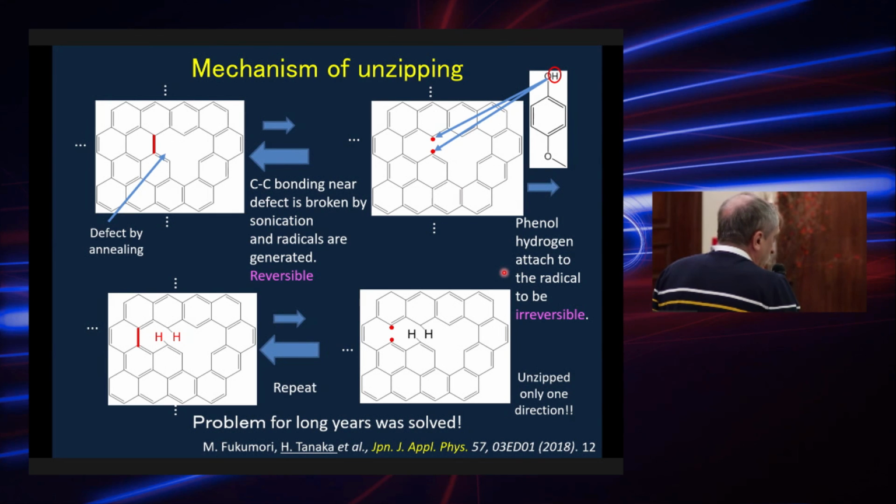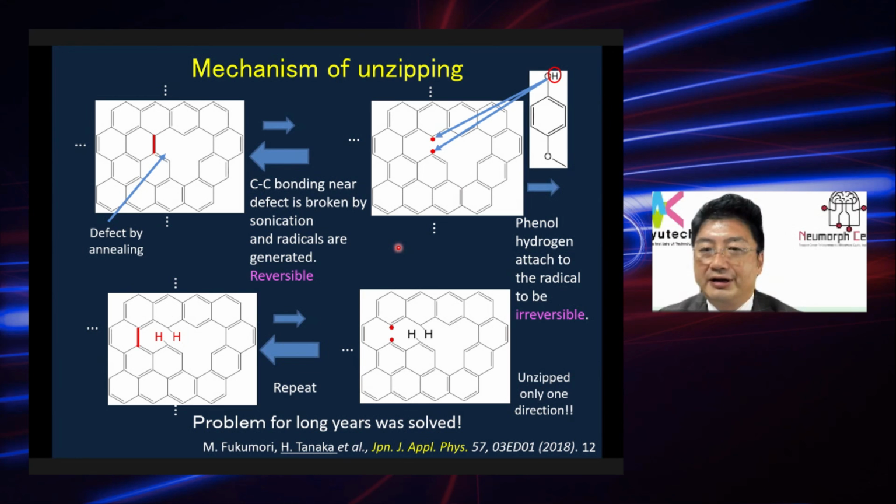It's a known problem, actually. What can I say about this method? Because of the chemical unzipping, your nanoribbons may have different vacancies, different defects, and so on at the boundary. So each state should be present. But no. By checking with AFM, Raman, or other methods, our graphene nanoribbon has almost no defect.